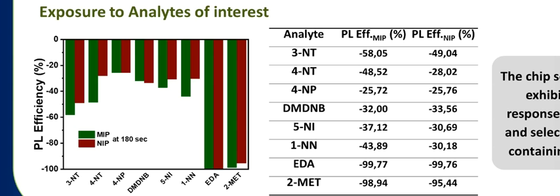This figure shows the measured selectivity of the MIP and NIP films to different analytes for a fixed exposure time of 180 seconds. The PL intensity decreases significantly when exposed to nitro-containing molecules, depending on the nitro compound. Therefore, our chip sensor approach exhibits very fast response, a few seconds, and high selectivity for nitro-containing compounds.